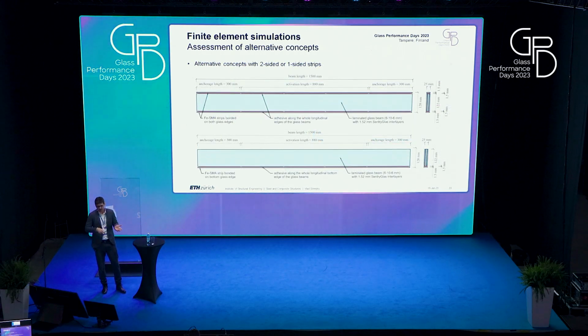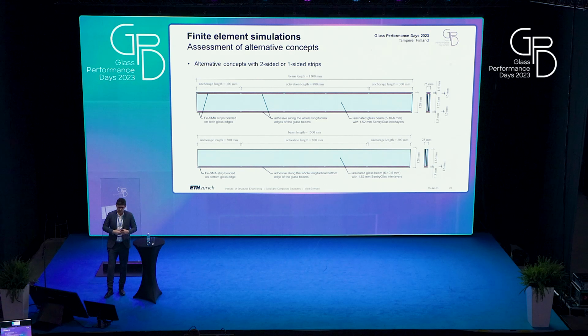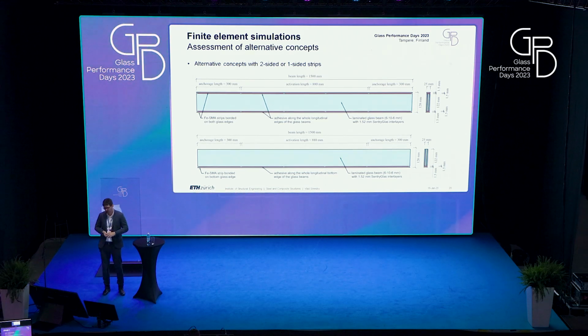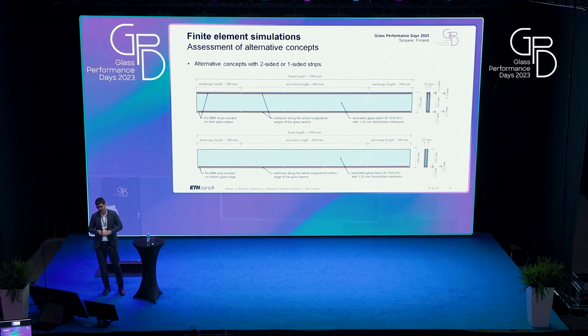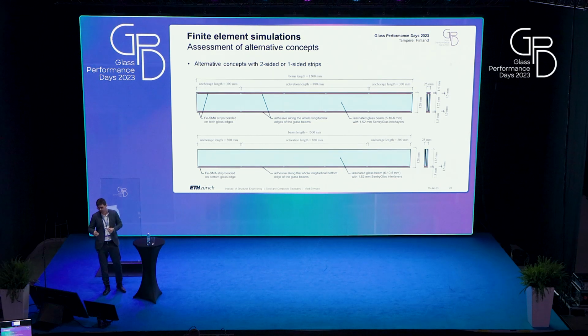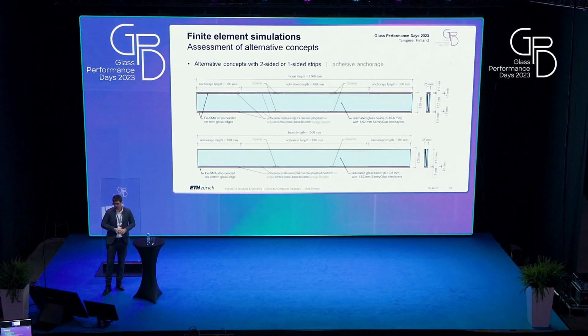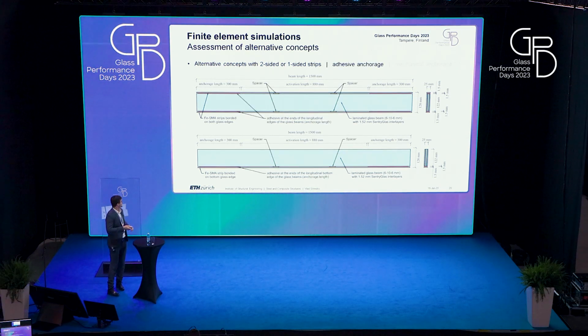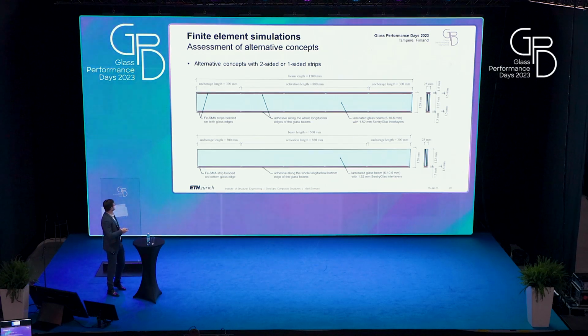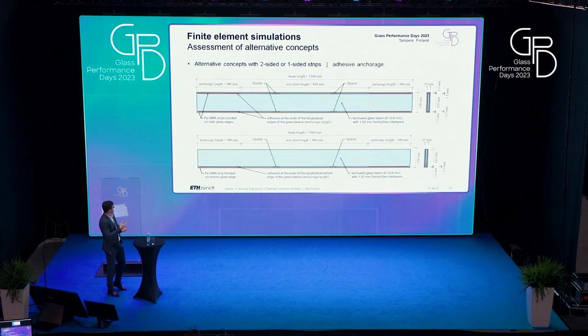So after validating the model, we decided to look at different concepts based on finite element simulations, and we assessed also concepts with strips only along one side, only along the bottom edge. Also systems, these two look quite similar. The difference is that in the middle part there is no adhesive, so we have adhesive only in the anchorage areas.